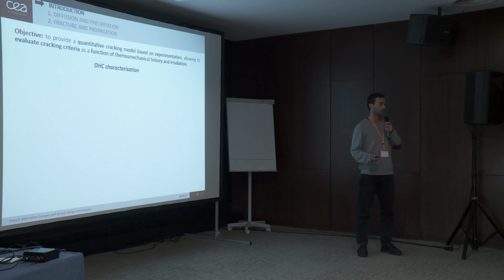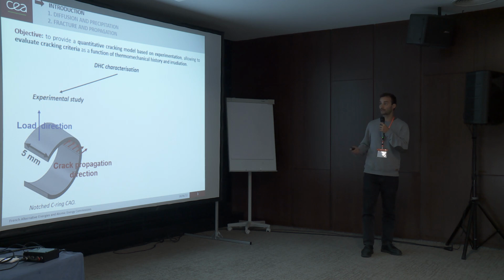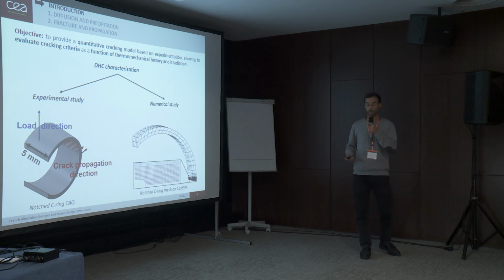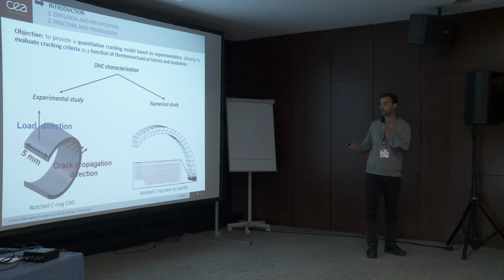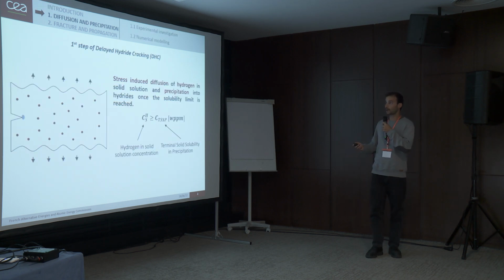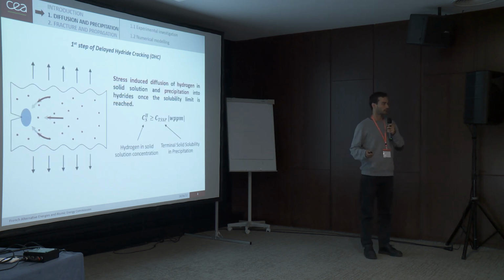So to do that, we set up an experimental study in order to investigate DHC crack propagation in the radial direction of fuel rod cladding, thanks to this specimen geometry called notched C-ring. And we set up a numerical study to model DHC and to quantify the cracking criteria. And of course, those two parts are interacting. So now I'm going to talk about delayed hydride cracking.